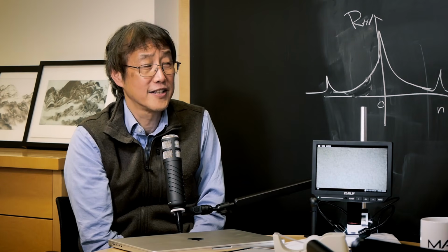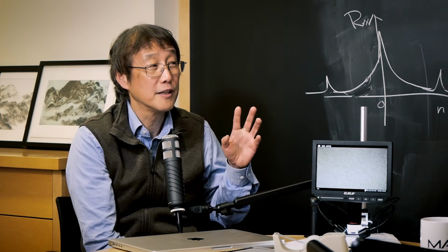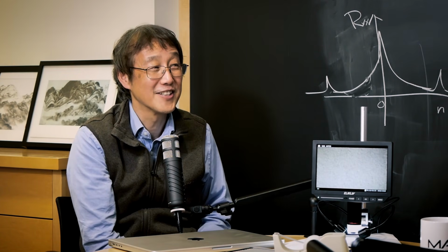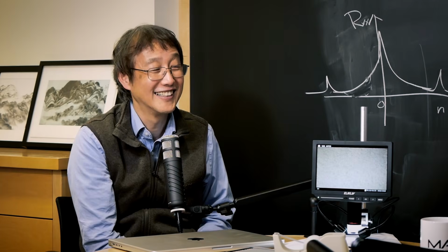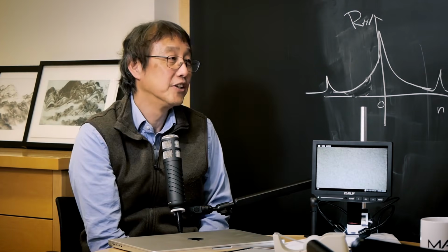So how precisely do you need to get to, from Pablo's perspective? You have to really align within 1.1 degrees. Oh, wow. Even 0.3 degrees away, you don't get the superconductivity, right? So it is really sharply tuned. And how is the alignment done? Ask Pablo. But do you also do twisting? No, we don't do that.